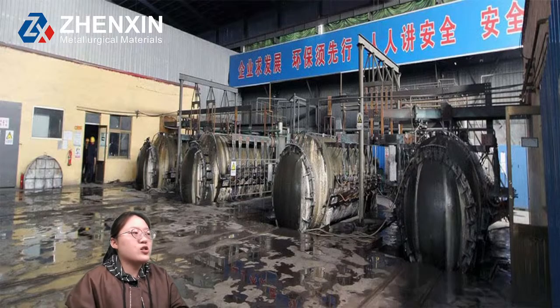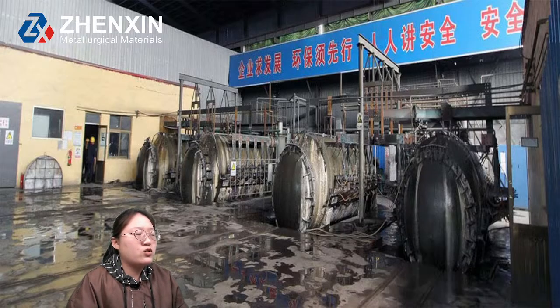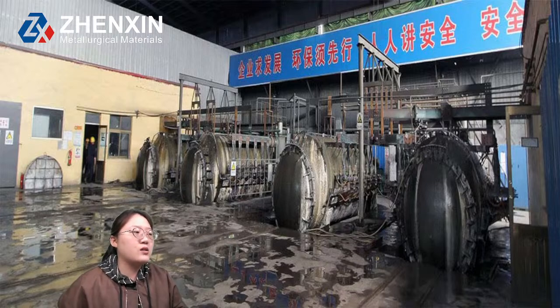For its features, the first is stable nitrogen content, high density, high alloy absorption rate, melting point about 1700 degrees Celsius, and ferrochrome nitride can partially replace nickel elements and reduce the production cost.